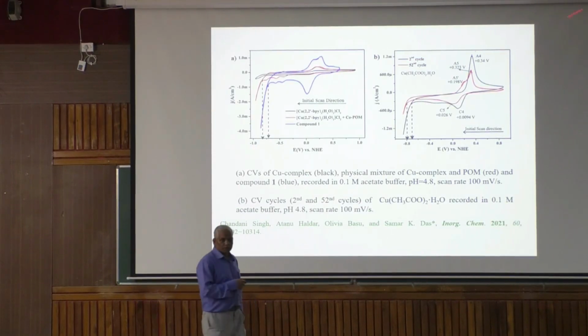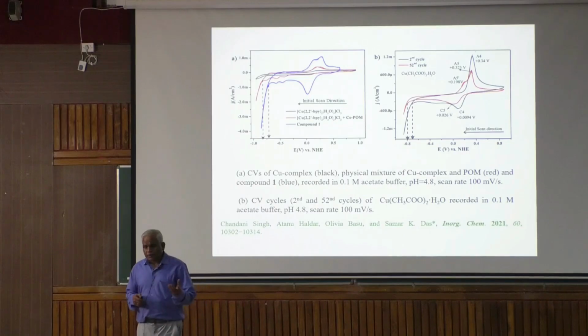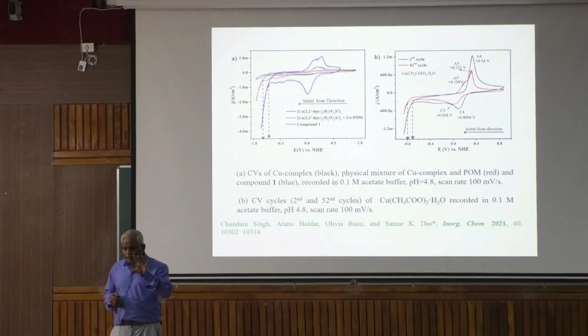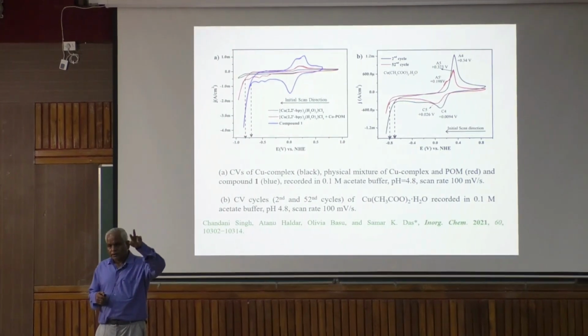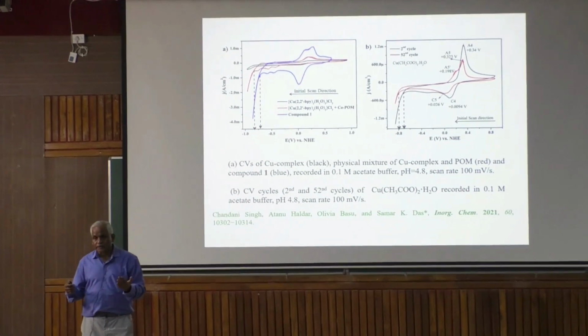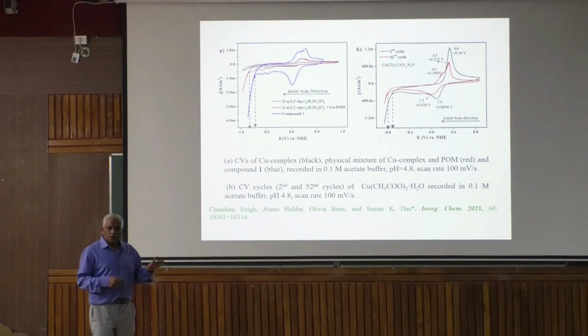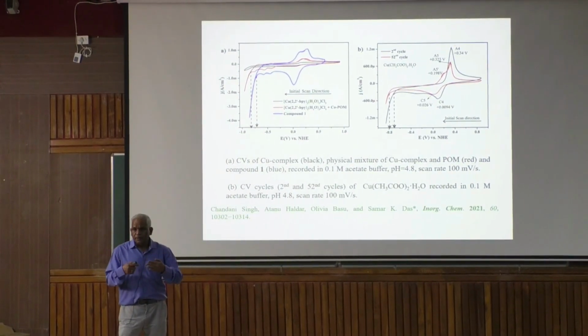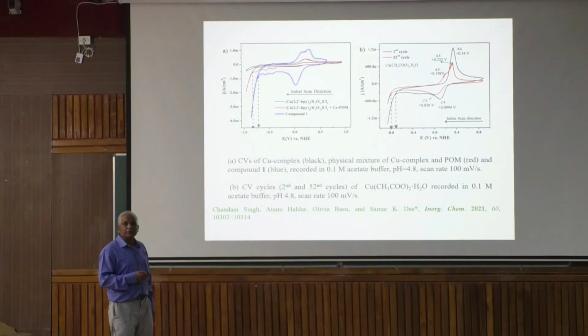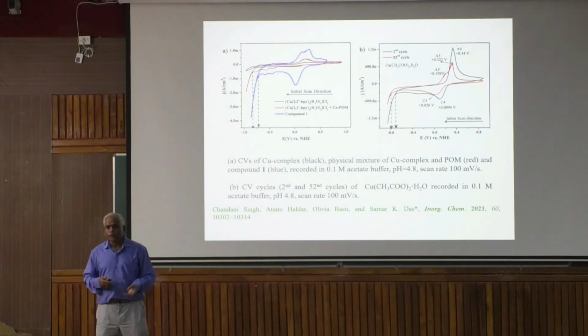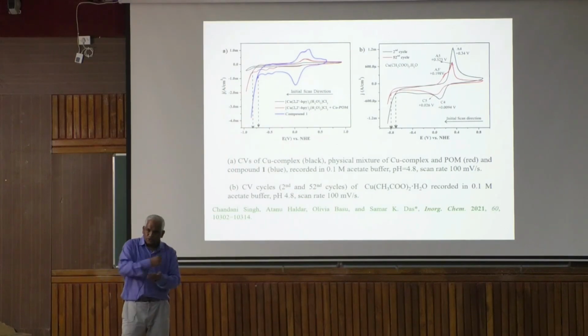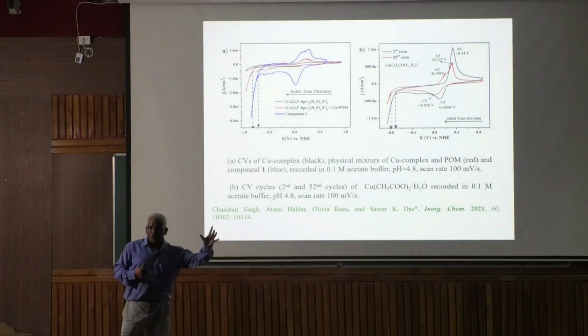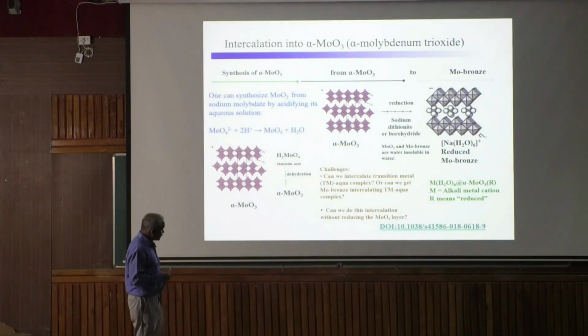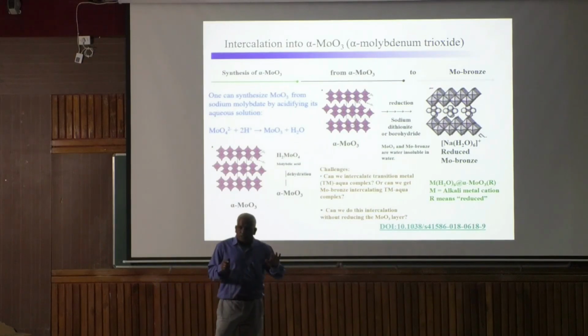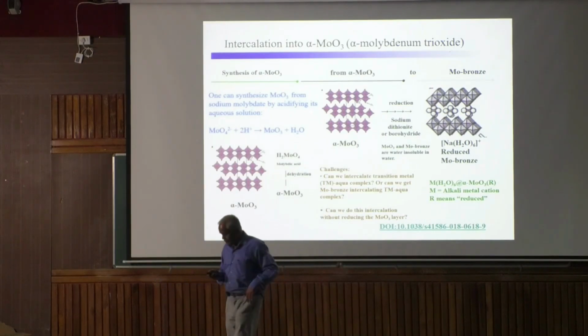We did a lot of control experiments, of course, because you may say that the copper bipyridine aqua compound is attached, but it may detach during the catalysis. So we did a lot of control experiments, and we proved that only when attached is it stable and gives continuous hydrogen evolution. Otherwise, a physical mixture doesn't give it. What do I mean by a physical mixture? You may take copper acetate or copper chloride and bipyridine, mix and grind together and do the catalysis. It will not give. So this is the story of the heterogeneous system by coordinate covalent bond attachment.